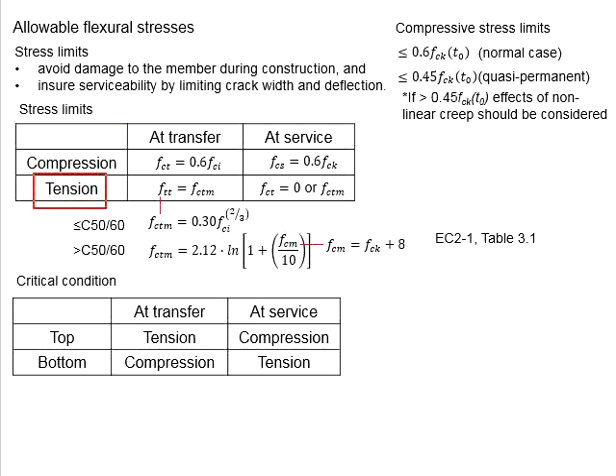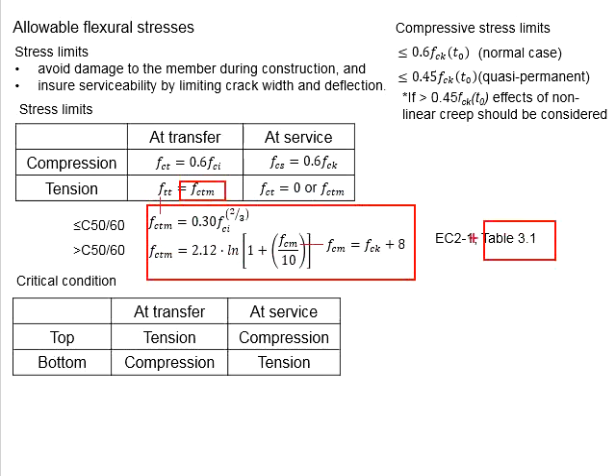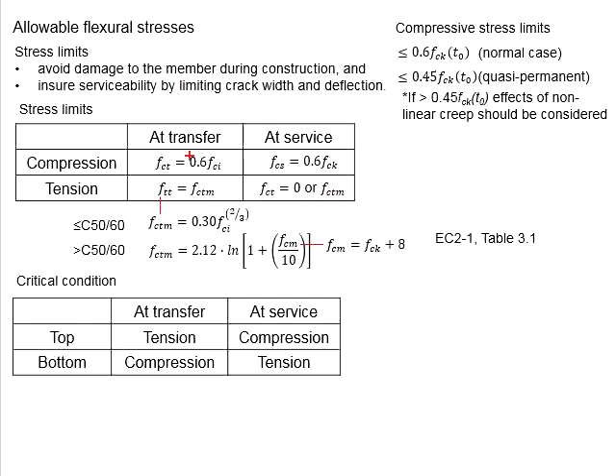Next, we look into the tension stress limit. It is normally governed by FCTM, the concrete mean tensile stress. FCTM can be determined from these two equations or referred from Table 3.1 of Eurocode 2 Part 1. For the concrete grade less than 50, the FCTM will be obtained from this equation. It is in the functions of mean compressive strength of the concrete, which is FCK plus 8.